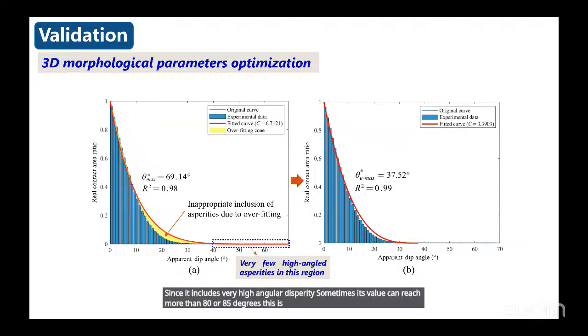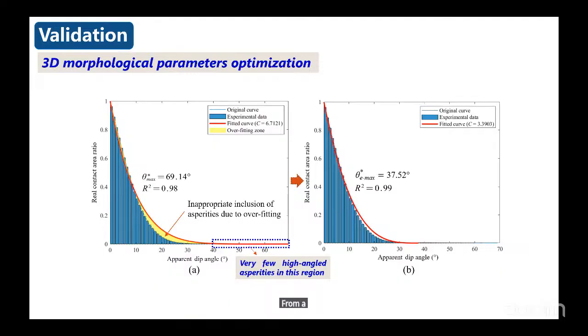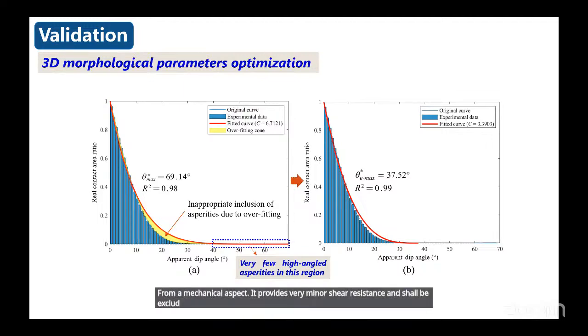This doesn't make any sense. But these asperities are very few and very tiny. From a mechanical aspect, they provide very minor shear resistance and shall be excluded from the fitting. Thus, we optimize this fitting process by trial and error to achieve the best performance.